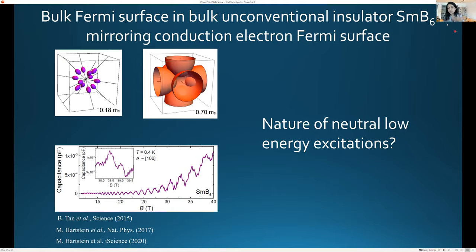We could also invoke things like what I mentioned about the mobility being quite poor, especially at the surface of the material. And the bulk, well, the mobility isn't just poor, it's an insulator in the bulk. So if one were to look at a metal, then one could explain it because of various aspects of the Fermi surface, with different techniques more or less sensitive. I think in this material, we should be more open to the possibility that there's some more profound reason connected with the origin of the quantum oscillations that is causing it not to show up in the electrical resistivity and only show up in the magnetic torque, which is coupling in a different way.